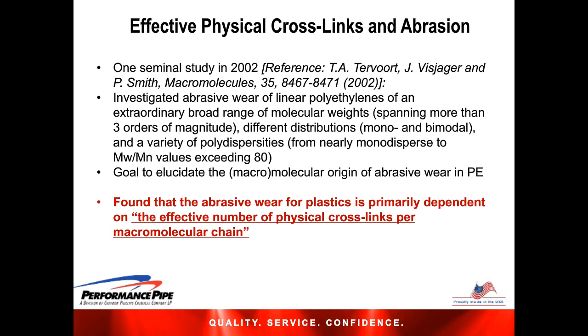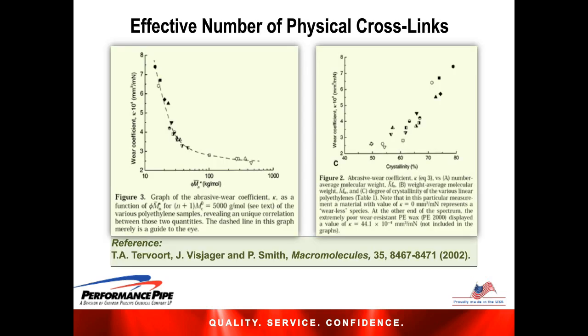We look here at a couple of key results from that published study, and shown in this slide are basically two of their plots. The left one is the wear coefficient, or the wear rate, as a function of this parameter phi mn star, and the right one is the wear coefficient, or wear rate, as a function of crystallinity.